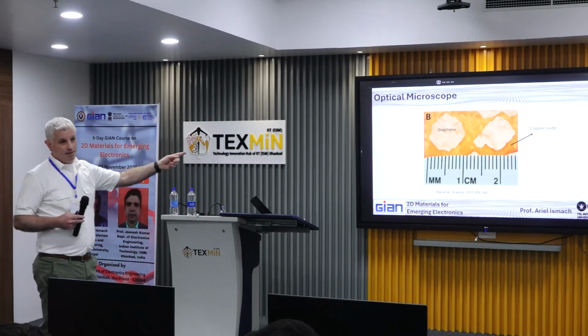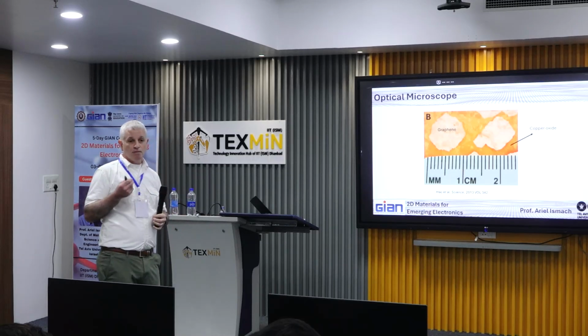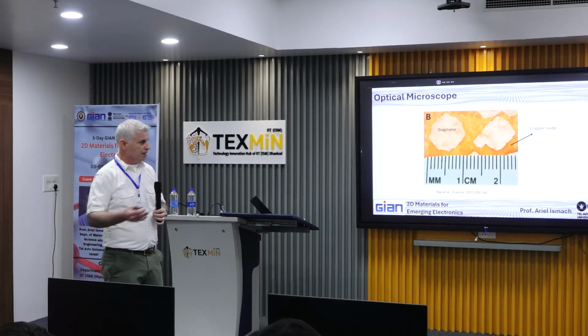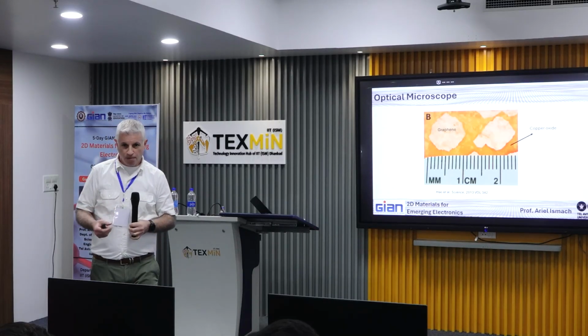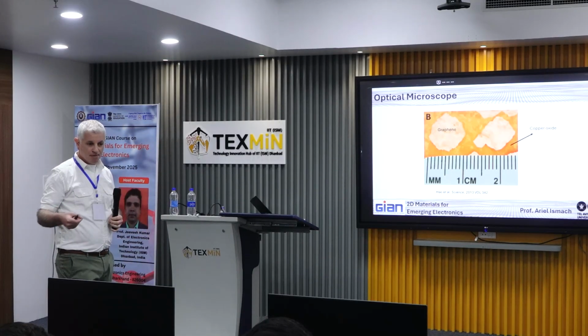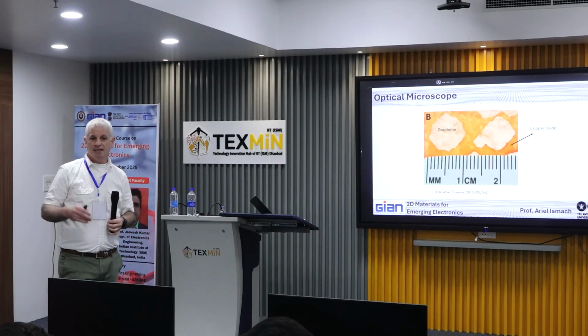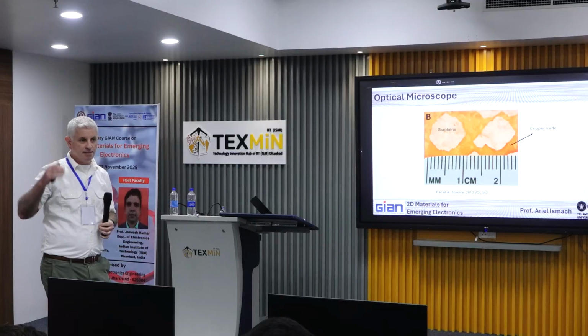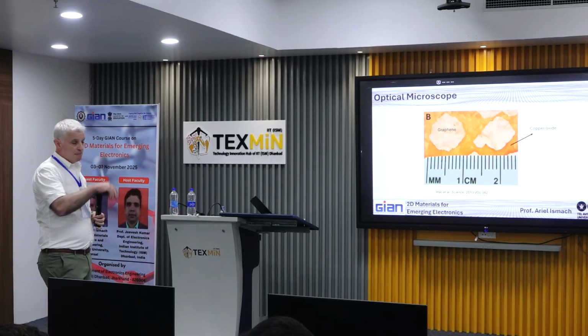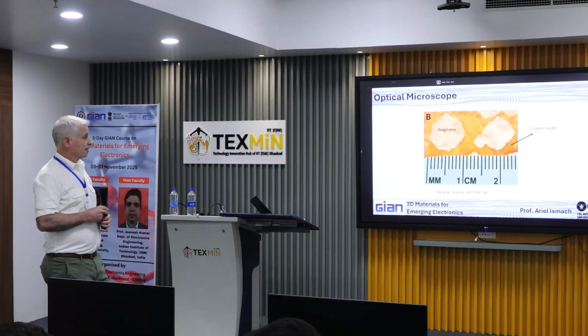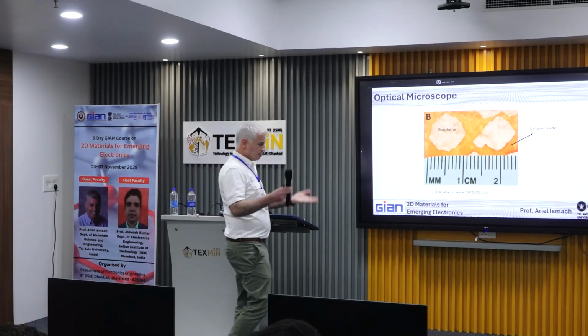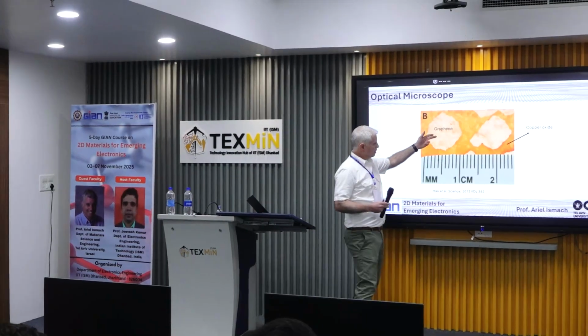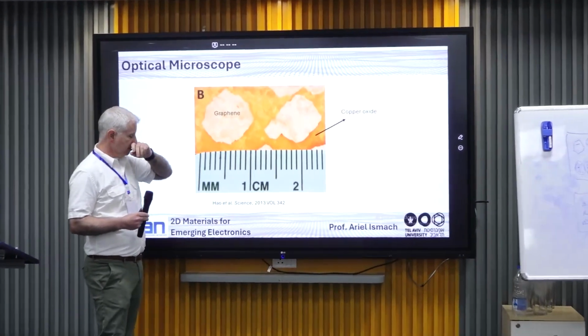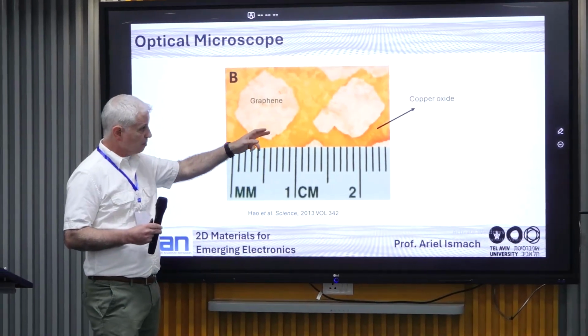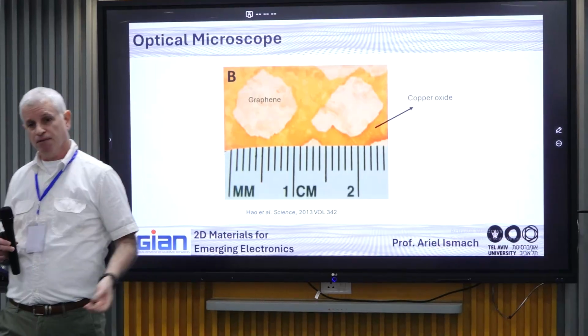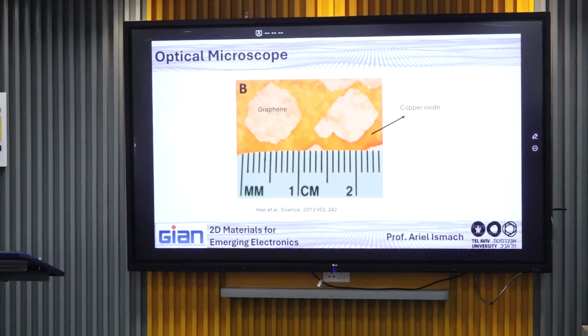You can expedite, by the way, the oxidation. If you really need to know if you have a continuous layer, if you really need to know how the growth was, you can take out the sample and put it, for example, on a hot plate at low temperatures. The graphene can stand the high temperatures, but the copper will oxidize faster. And again, when you are checking two areas, the kinetics are what is important for you. So here the oxidation is much slower, here much faster. So you can differentiate, very simple.